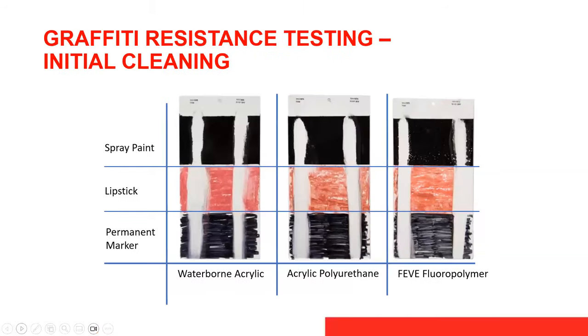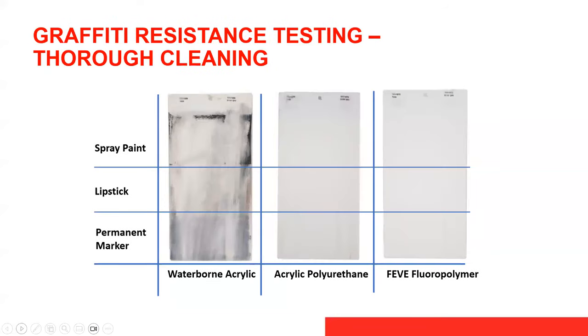And so as part of this process, we'll do an initial cleaning just to see how quickly we can wipe that graffiti away. And then we'll do a very thorough clean. And this is where we will take very careful notes to see how much of the area was able to be cleaned and how much returned to its original appearance. And so in this, you'll see that the waterborne acrylic did not fare very well, which is not surprising.